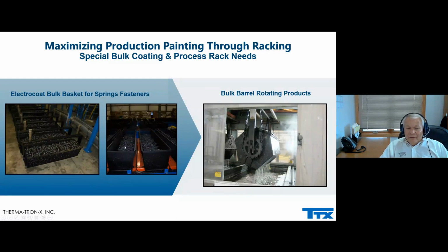The fastener market is very big in construction fasteners and even in some of the automotive fasteners where you use barrel coating. Barrel coating allows you to minimize the touch marks by shifting the parts during the process of electrocoating. So, for example, when you dip this barrel into electrocoat, you can orientate the parts after a minute and shift those parts a little bit to allow more deposition on the touch mark areas. So this is very successful in the marketplace today.